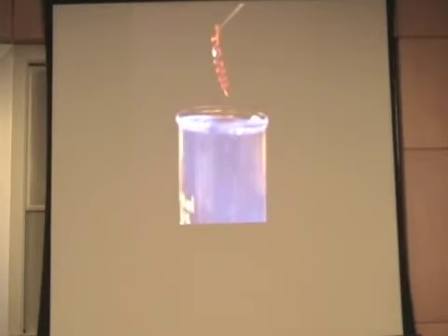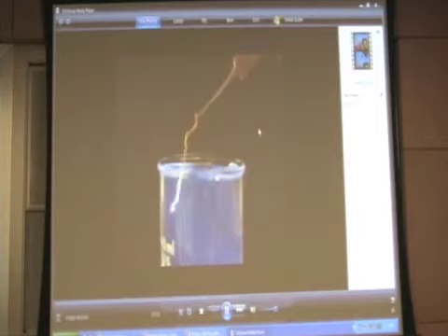And so when we combined these materials, we found that the shape memory went in sync with the color change. In the high temperature state where the dye exists as a so-called monomer, it fluoresces green. Once we stretched it and cooled back to room temperature, excimers form and it fluoresces in a red state. However, and this is the fixed state, when we heated it again, recovery happened at the same time as the color change, which I think I'll show you maybe outside of there. Which looks like this. You can see the shape change in synchronicity with the color change.